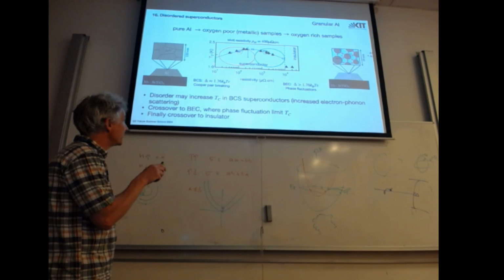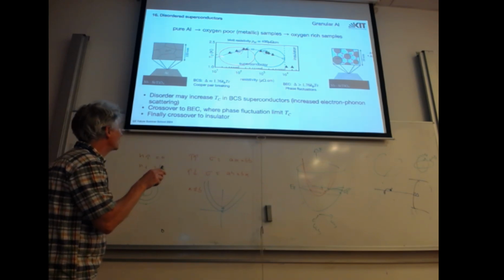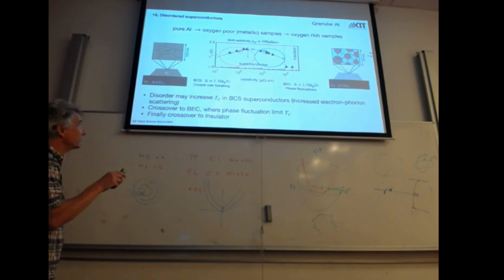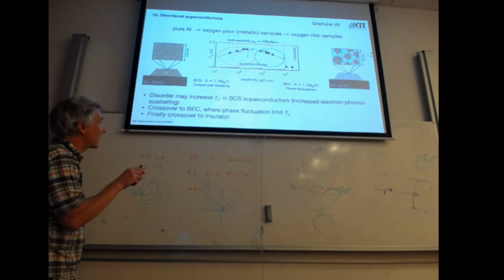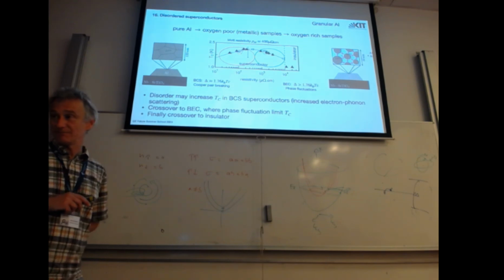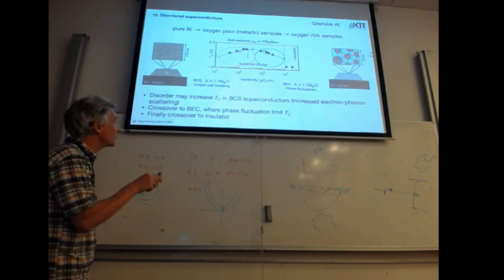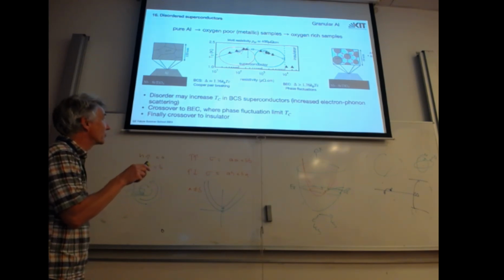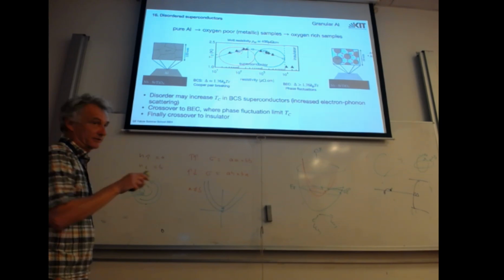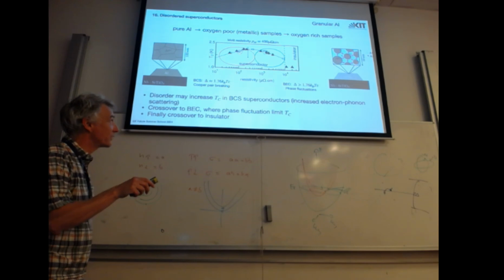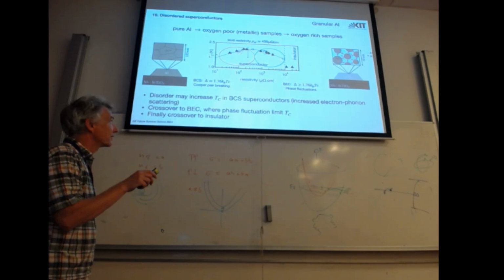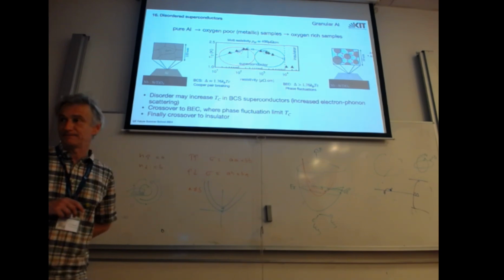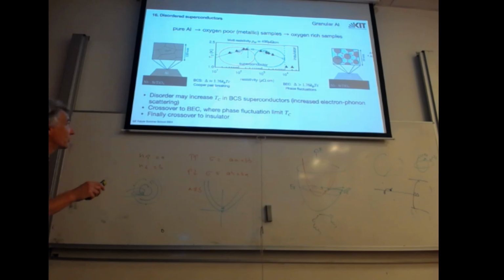If you measure Tc, you start with the Tc of aluminum around 1 Kelvin, and the more disorder you have, the higher Tc becomes until an optimal value, which is close to the normal resistivity, then it goes down. And eventually the system has so much oxygen that these grains decouple, and this turns into an insulator. So this is the superconductor-insulator transition.